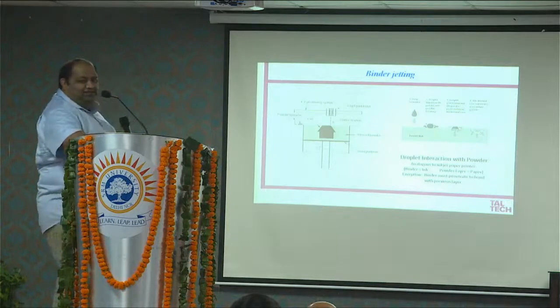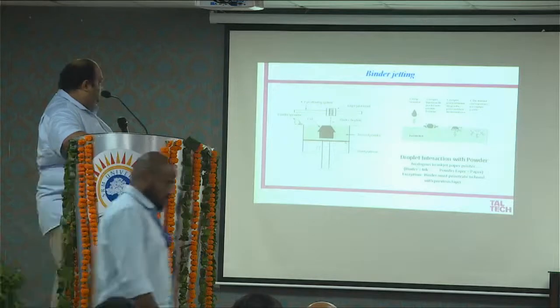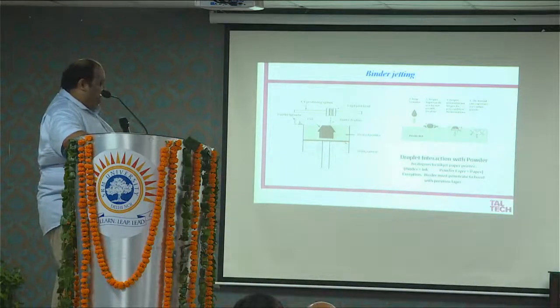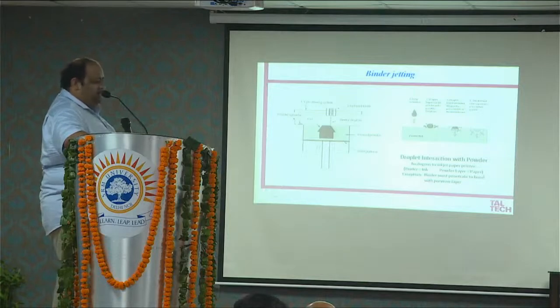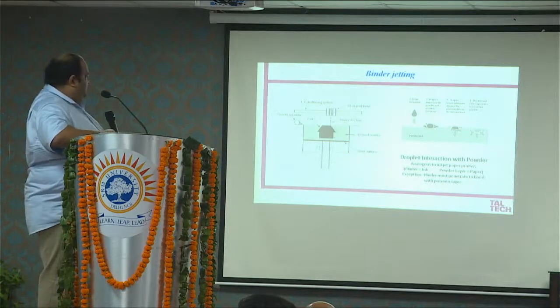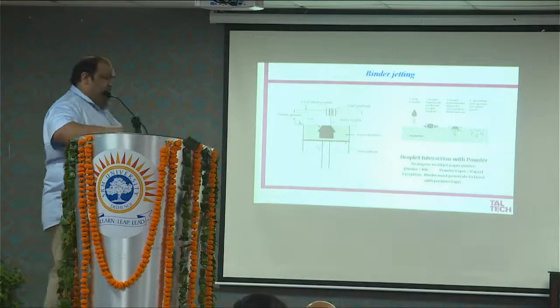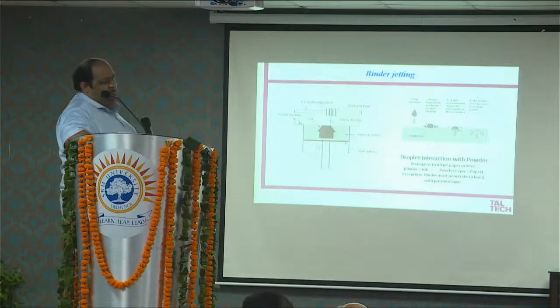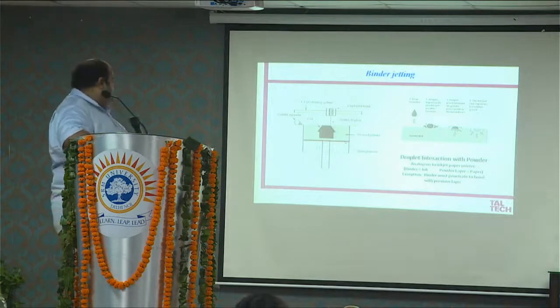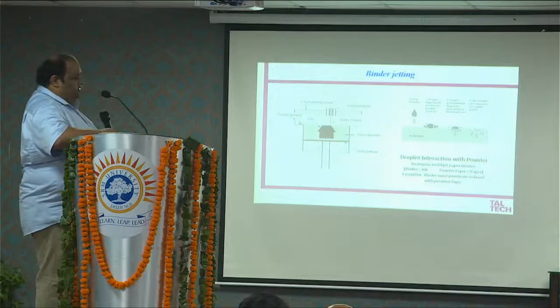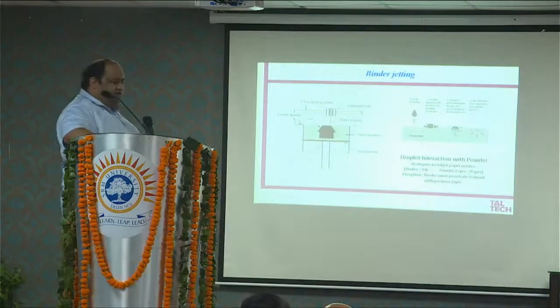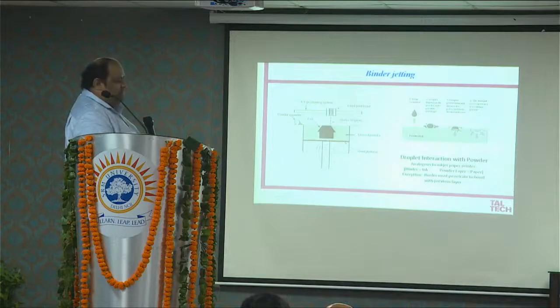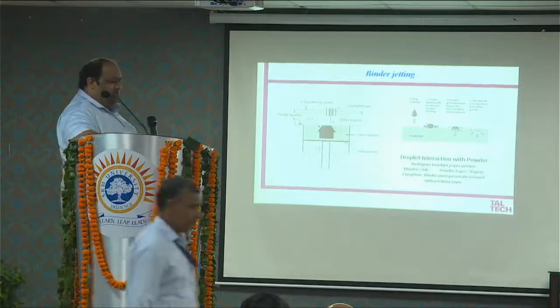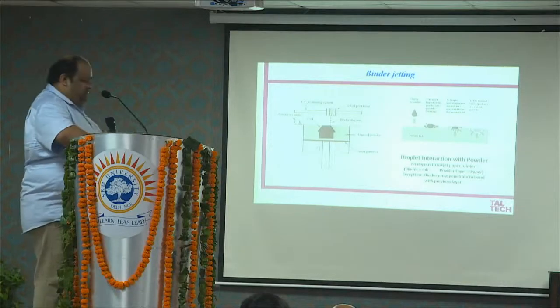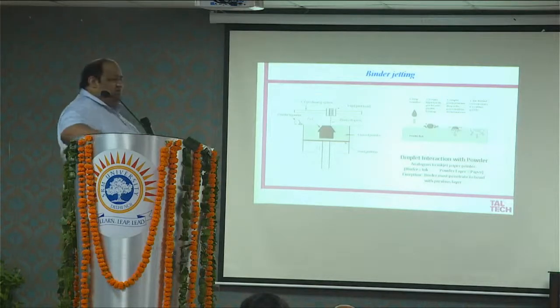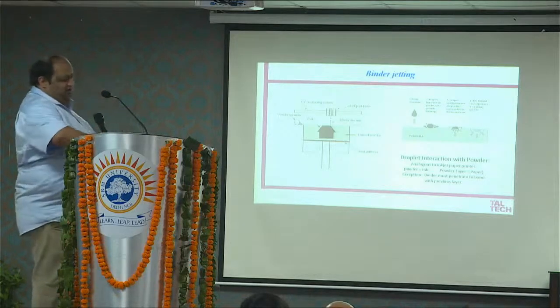So this is a multi-step additive manufacturing process where you initially get a green compact, and then the binder has to be debinded, and then you go for a sintering approach. So here you need to have conventional knowledge of sintering, because all the sintering-based defects you have in the normal sintering process, like porosity, distortion, warping, etc., you will also see in this particular process, apart from the biggest advantage of producing components in a three-dimensional manner with no restriction on the shape and size.